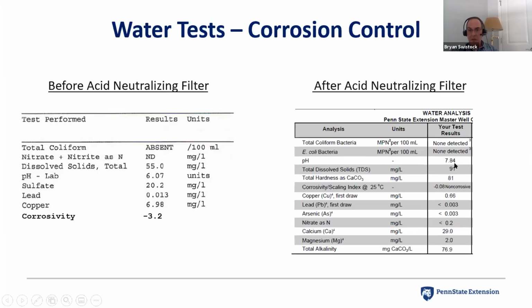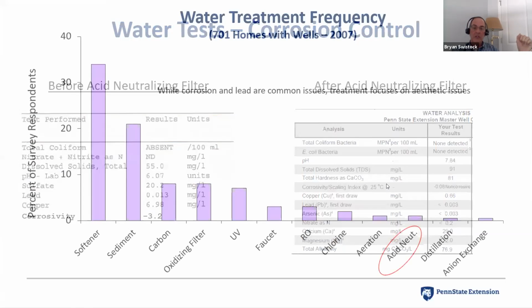And after the acid neutralizer, we have a pH of 7.84. We've got a little bit more hardness now. We're at 81 milligrams per liter. The pre-filter was much lower hardness, but we notice we have no detectable lead, and our corrosivity index is now non-corrosive. It's negative 0.08. So in this case, the filter worked beautifully. It raised the pH, got rid of that corrosion index problem, and brought our lead level down below detection. And so now we're protecting the plumbing from leaks, and we're not dissolving lead, we're not dissolving copper either, at least not enough to worry about. And we've been able to solve the problem just purely through corrosion control.